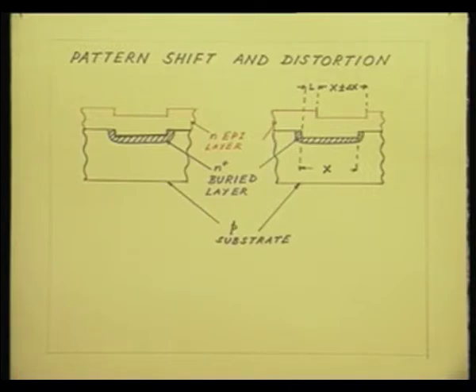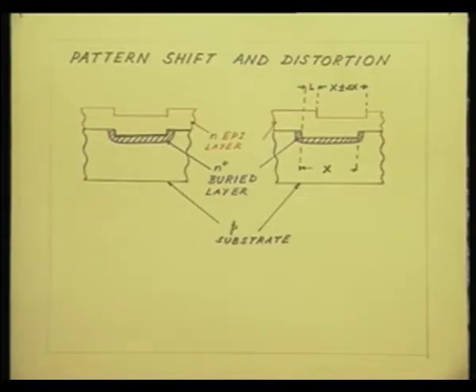So, now if I grow an epitaxial layer, I would expect it to be aligned with this step, so that the epitaxial layer should also be formed like this, because everywhere I expect that, okay, I am growing say 5 micron from the substrate. So, this height should be 5 micron, I should expect it to be properly aligned. Now, this proper alignment is going to play a very important role in my further processing, because this step, once the epitaxial layer is formed, you see I have no way of knowing where the underlying buried layer is. So, this step is only going to tell me where the underlying buried layer is, so that I can properly put my base mask and the emitter mask, so that the transistor is fabricated in this active region and not this way or that way.